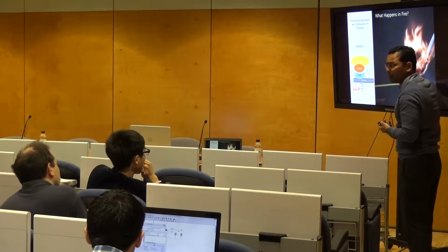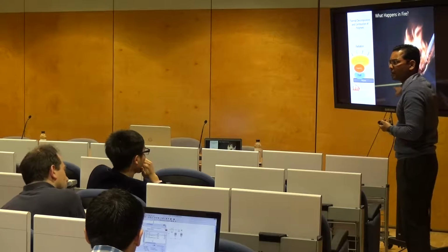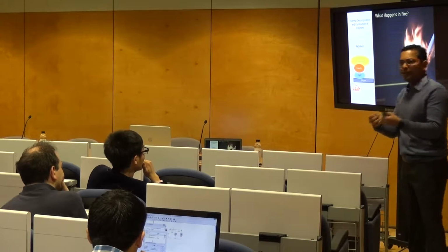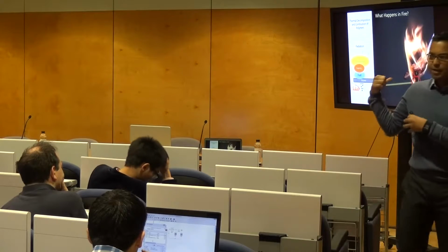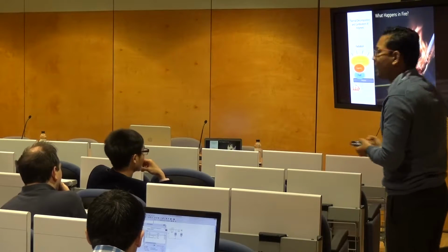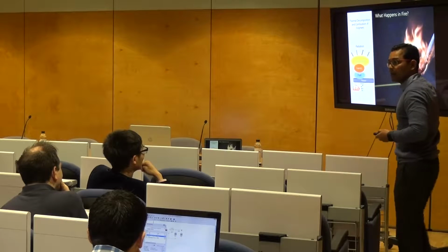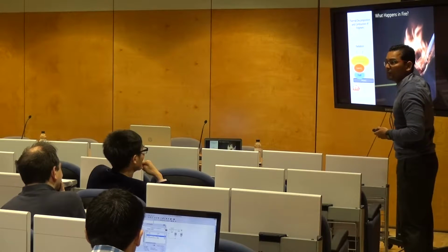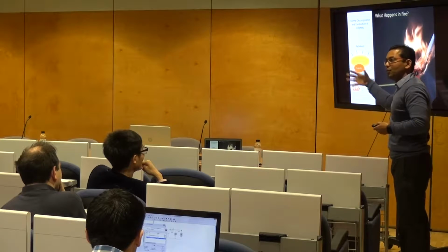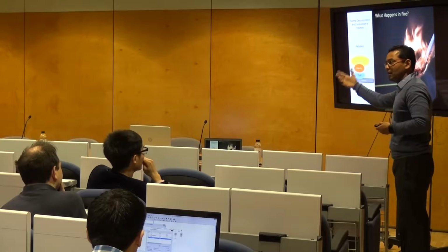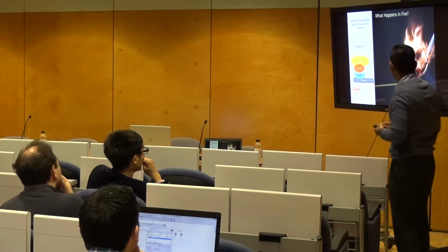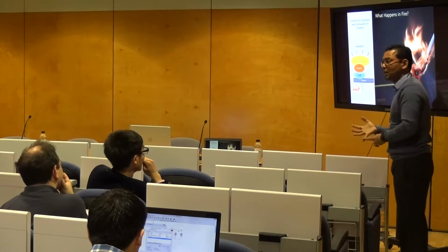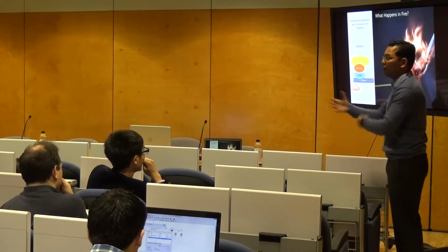And then you can see the melting behavior, which is enhanced by the fact that the phosphorus which is present in the polymer breaks it apart, or it helps in hydrolyzing the material, in this case polyester, into smaller fragments, which drip away. Okay? And that is another way the flame retardant actually works. And then you can see the bright yellow flame. The bright yellow flame is actually the phosphoryl radical, okay, an oxophosphoryl radical. Okay, so there are certain things you can see which clearly indicate how polymers decompose, and if the flame retardant is there, what is happening, I would say.